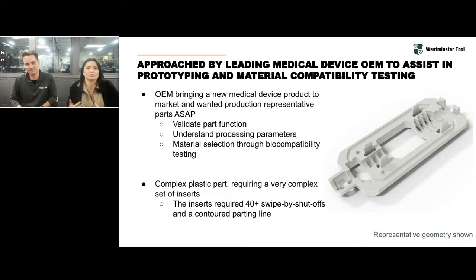So in this case, we were able to figure out what our most critical areas were. We wanted to make sure we had a solid shut off. And just to throw out, because this was a new product that was being developed, we're currently in the production mold build of it. The part you're seeing here is not identical. It's representative. So it actually had more shut-off conditions. It had more geometry, and it was larger. So it's a bit more difficult than what you're seeing here.